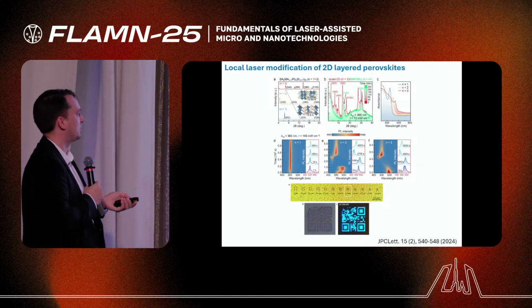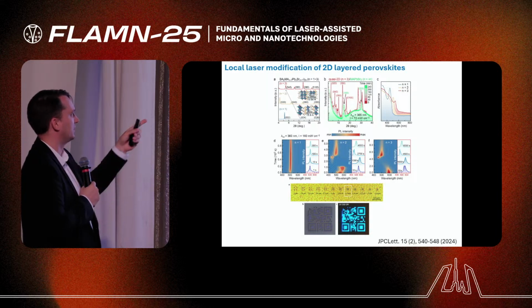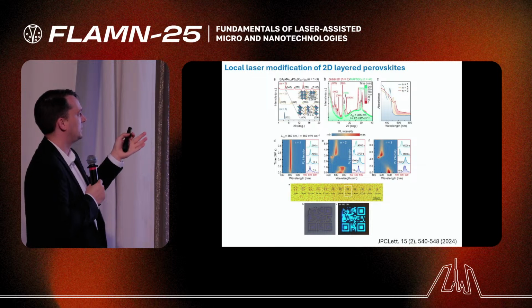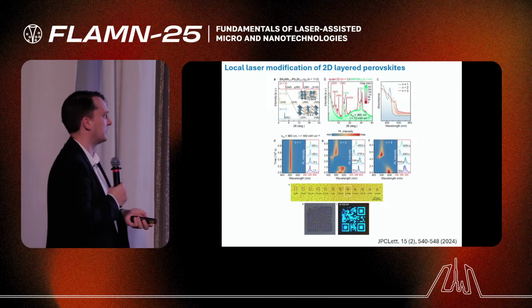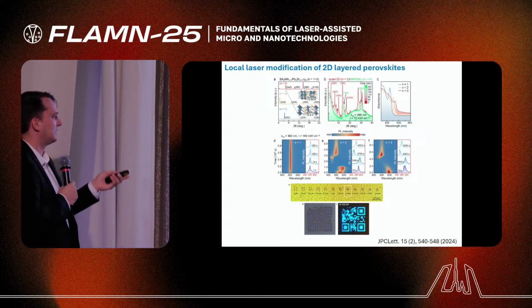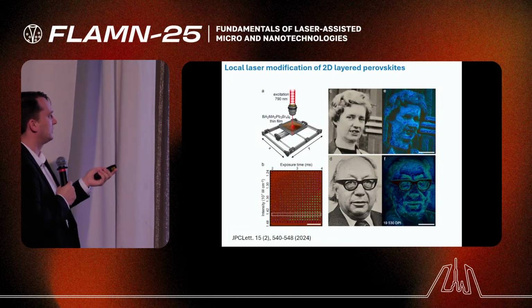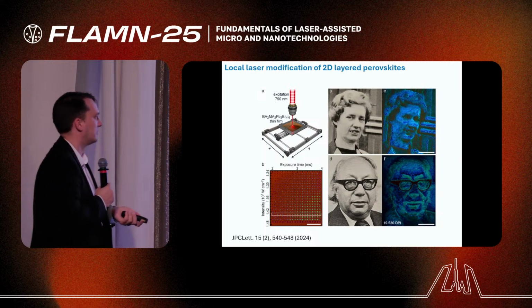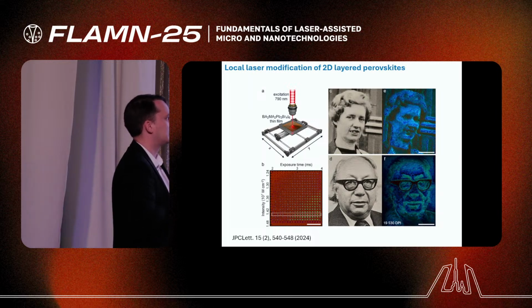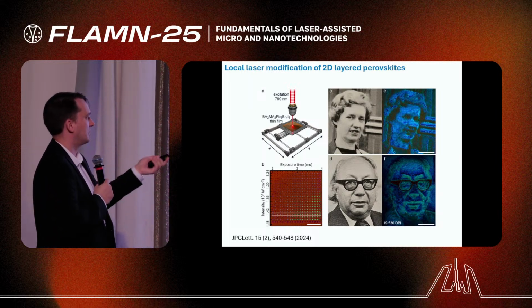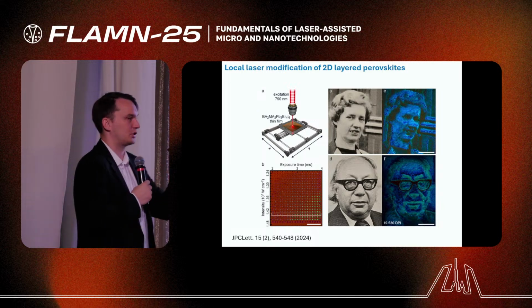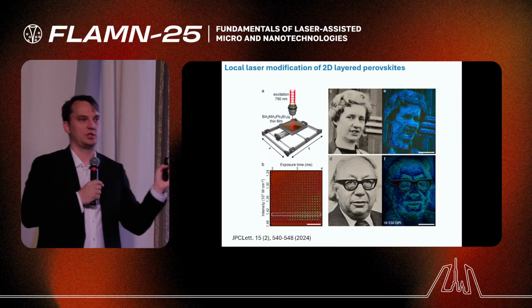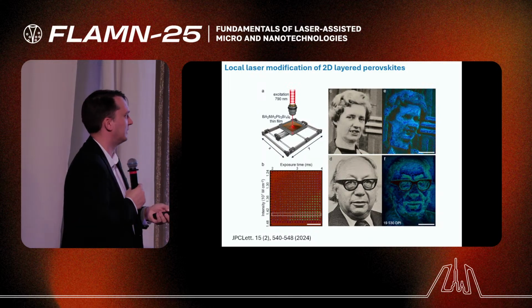So it changes the emission properties. If we have n equal to 1, it's just a single layer material. But if we have a multi-layer system, we can convert it to bulk and write, and each dot will emit light with a different color. Here is also an example of pictures which we created from this material, and in photoluminescence you see that each dot has a slightly different color, created in a programmable way. So this is how we used the conversion of layered perovskite to bulk perovskite, where we lose quantum confinement and change the light emitting properties.